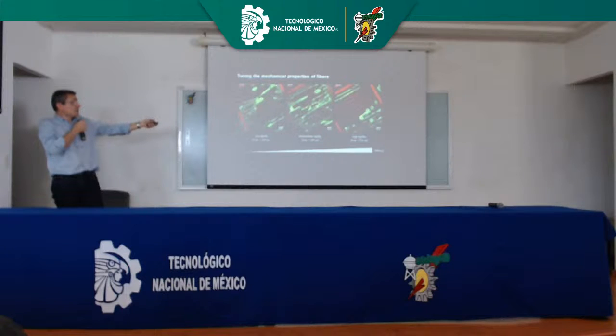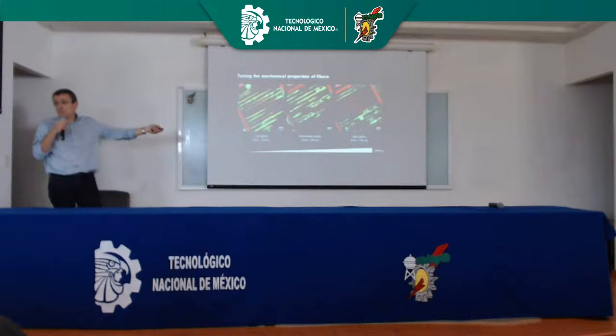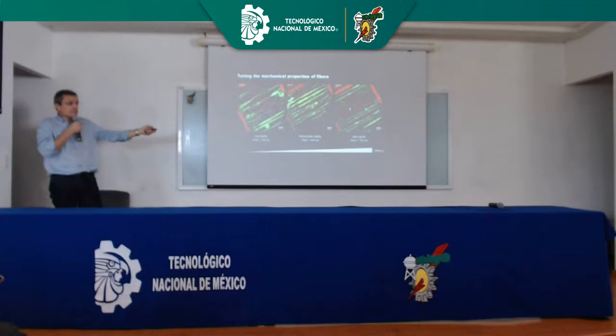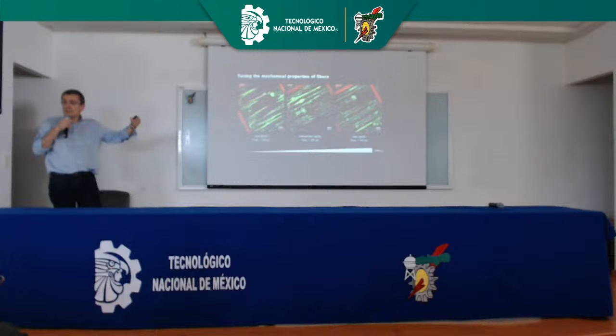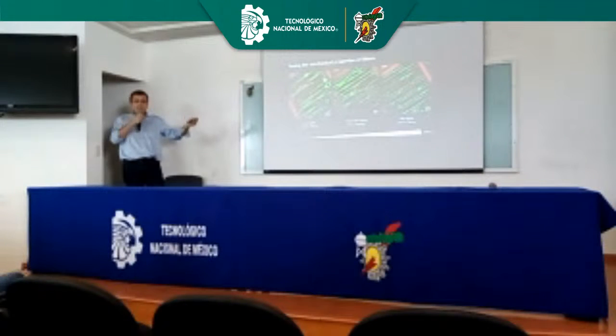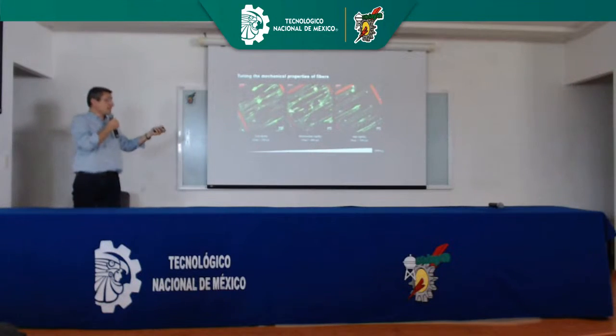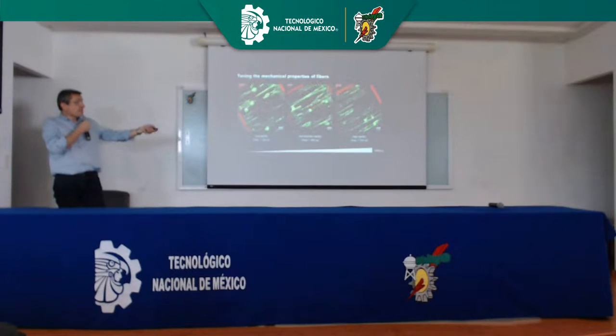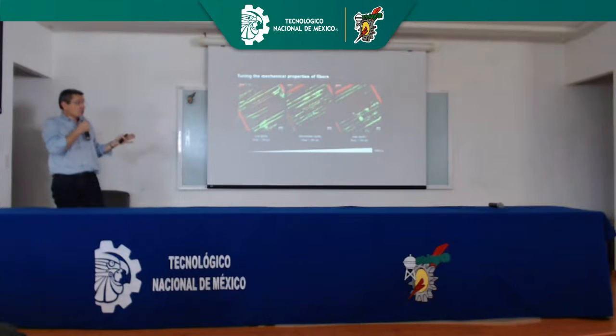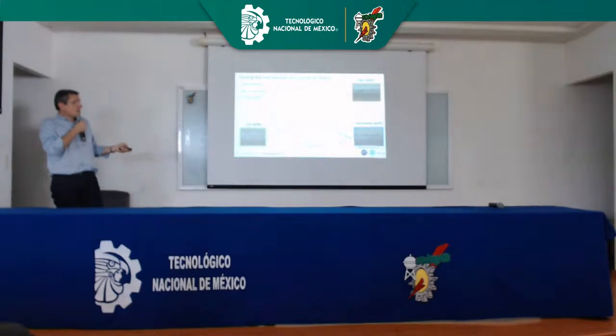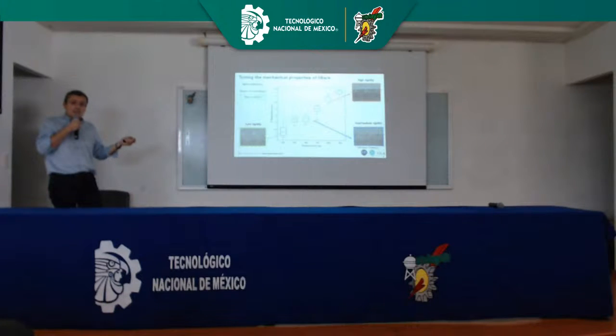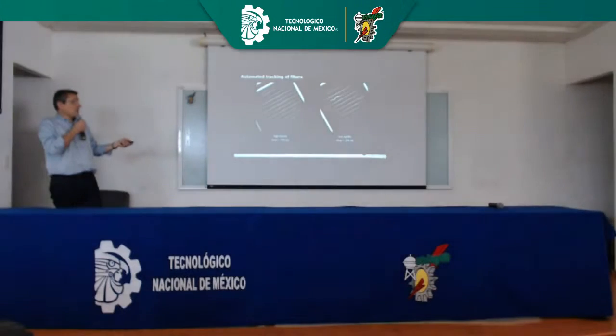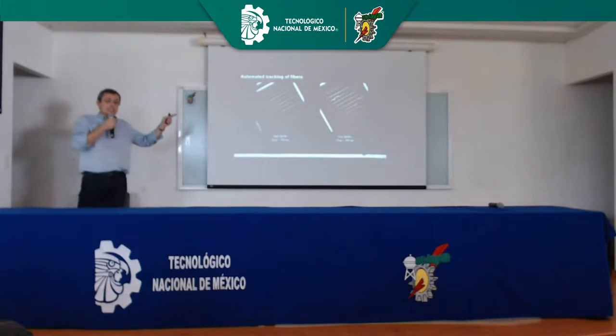At low rigidity, cells go in and they deform the fibers completely. They deform, but if the cell then goes away, the fibers relax the deformation and we can recover the form of the fiber, so they are really elastic. As opposed to the system where we have high rigidity and there is almost no deformation. So we are characterizing this system, and the idea is, in the future, to link the deformation of those fibers with the force that cells apply locally on the fibers.